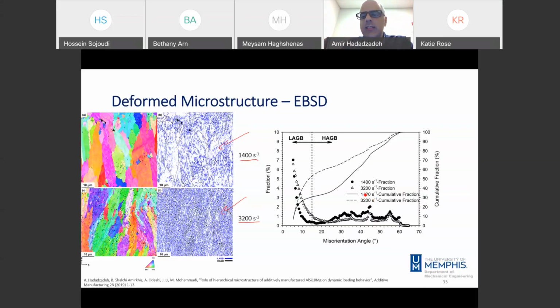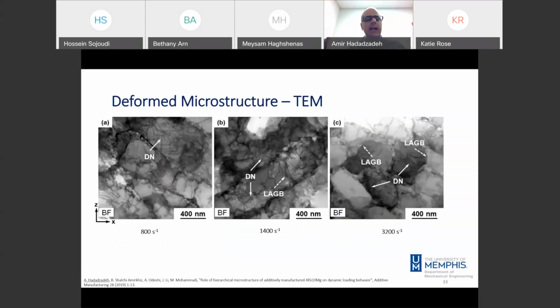If we analyze that, we see that for the 1400 per second sample, only about 30% of the structure is covered by those networks. However, by increasing the strain rate to 3200 per second, now about 60% of the grain structure is low angle grain boundaries. To analyze that, I studied the structure by TEM.